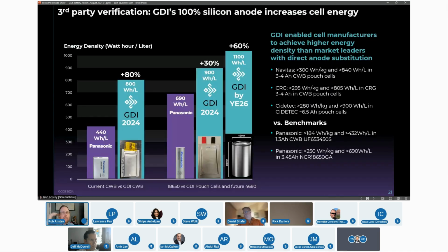Now, we also sent anode to Navitas in Michigan, CRG in Ohio, Cidetec in Spain. And what they were able to do is make 3 to 4 amp-hour pouch cells with higher energy density than Panasonic. They were able to get over 300 watt-hours per kilogram and over 800 watt-hours per liter. In the case of Cidetec, they made a 6.5 amp-hour cell that hit 900 watt-hours per liter. No pre-lithiation, no next-gen electrolytes. Everything else in the cell was completely standard, completely off the shelf. And they were able to hit between 800 and 900 and approaching 300 watt-hours per kilogram, depending on your choice of cathode.